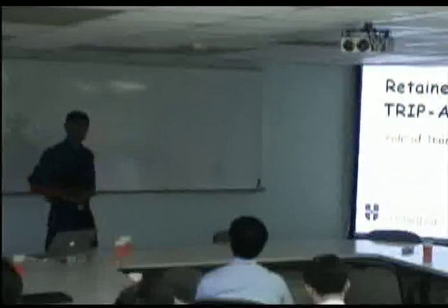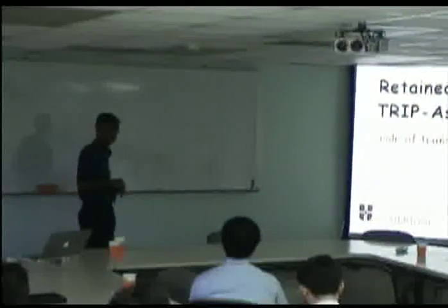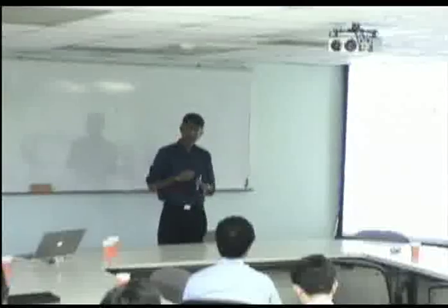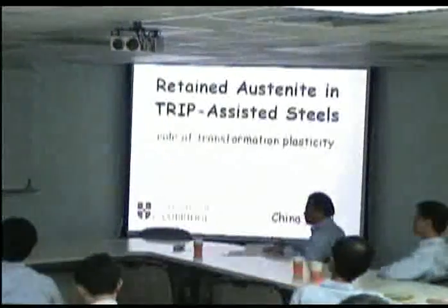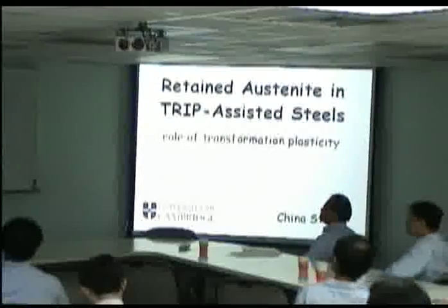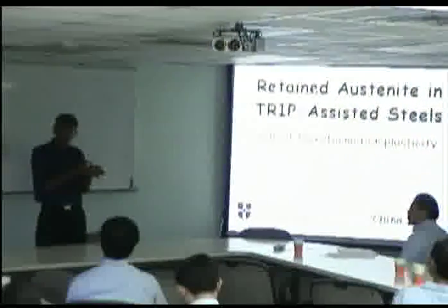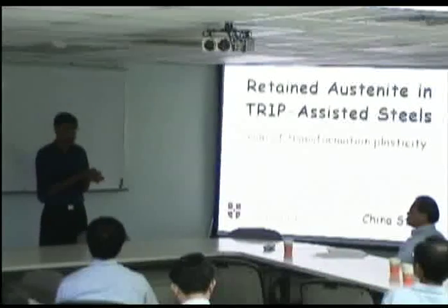So for many years now, people have been working on TRIP-assisted steels. By TRIP-assisted steels, we mean steels which contain about, say, 60 or 70% of allotriomorphic ferrite. The remainder is a mixture of bainitic ferrite and retained austenite, and there might be some martensite as well. And the typical composition of such steels is